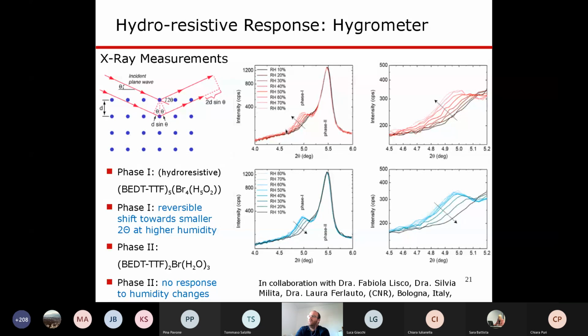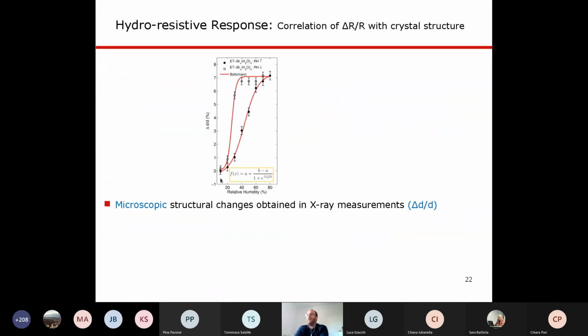So if we take from these figures over here, we can extract the distance. And this is shown over here. So at a higher and higher level of humidity, we see that this distance, which corresponds to the distance between the molecules, starts to increase, increase, increase. And then if we go back again to dry conditions, we go back to the initial point. So this shows us the microscopic structural change of these crystals.